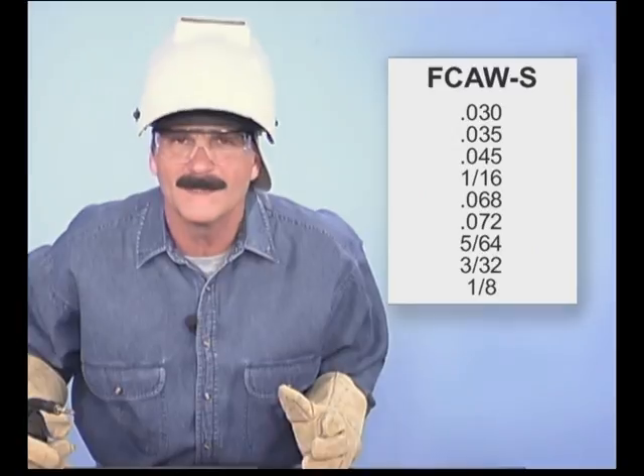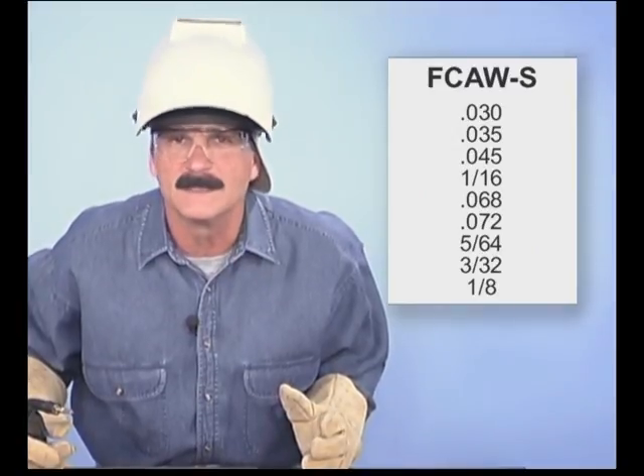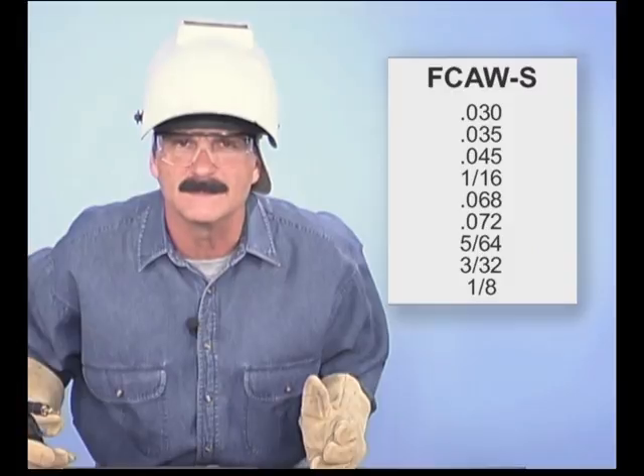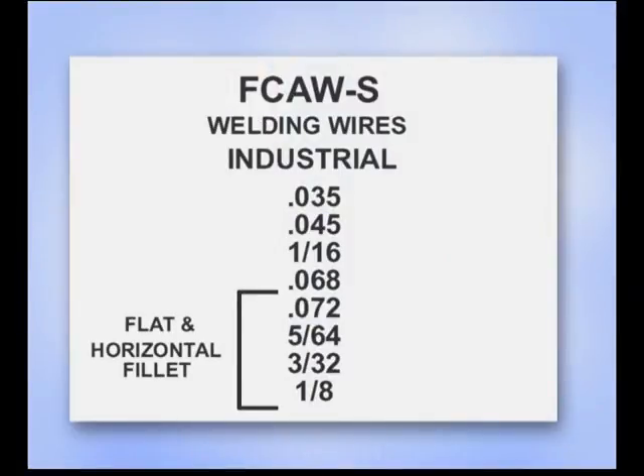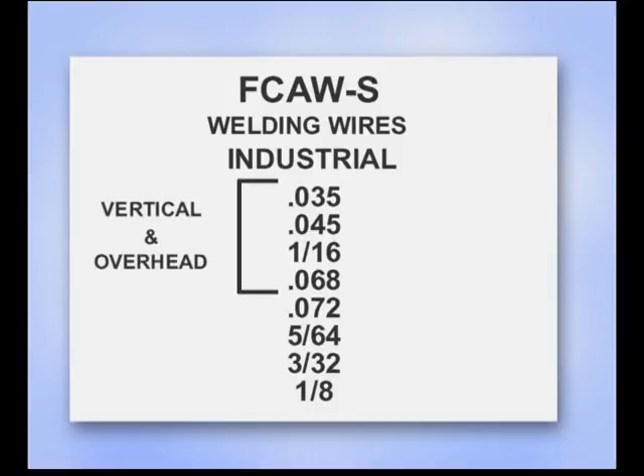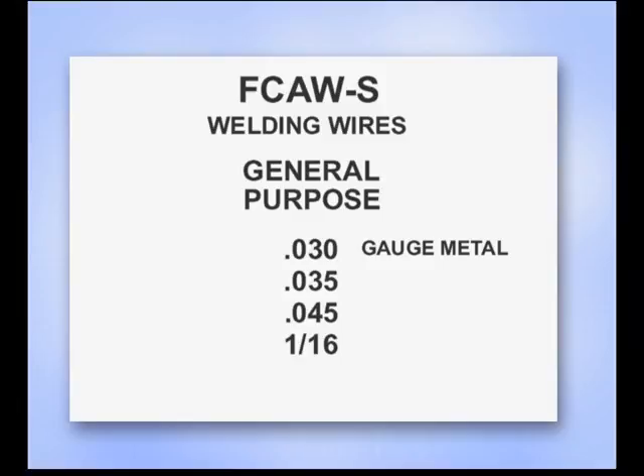The diameter of the wire is selected for the amount of filler metal deposit, and in some cases, the size of the welding machine. In the welding industry, larger diameter wires provide maximum weld deposits in the flat position. Smaller wires are used for vertical and overhead welds, depending on the thickness of the metal. For general purpose welding, where you're working with different metal thicknesses in different welding positions, it's more of a compromise. 030 works well for the thinner gauge metals. 035 is used when the metal is mainly 1/4 of an inch or less, and both of these are commonly used with the smaller wire feed machines.